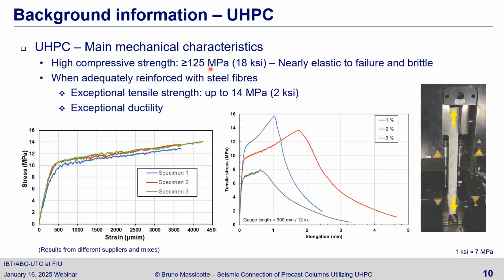I will be switching from SI to American units, but I've put the soft conversion in many places. So that is its characteristic in compression, but why do we use this material? Mostly for the tensile behavior, which will be around 14 MPa or 2 KSI for UHPFRC, compared to conventional fiber concrete. For example, on this side, it's UHPC with 2% fiber content, so it can go to stresses as high as 14 MPa, or about 2 KSI. And the beauty of that material is that in the stress-strain domain, once the matrix cracks here, you have a lot of strength and a lot of ductility. This is what we're using.